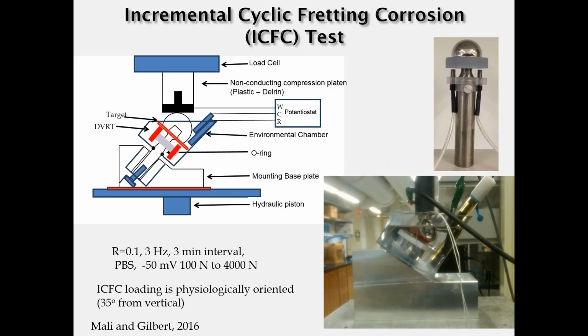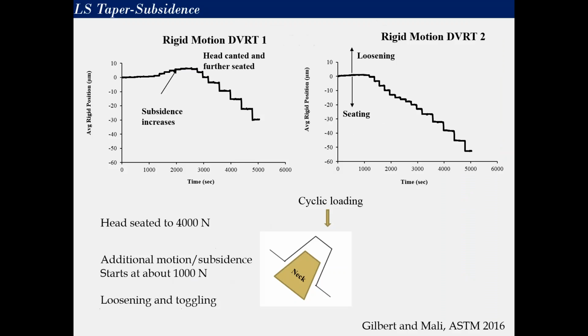This one particular test called an incremental cyclic fretting corrosion test is one that helps to do assessment of materials or designs or local geometry effects on the fretting corrosion of these modular junctions by applying a cyclic load, 3 hertz, 3-minute intervals in phosphate buffer with the sample held at -50 millivolts and going from 100 newtons to 4,000 newtons incrementally and measuring the response both in terms of the electrochemistry as well as the motion of the head onto the neck. And this is work that we've just recently had accepted for publication, will be coming out in 2016.